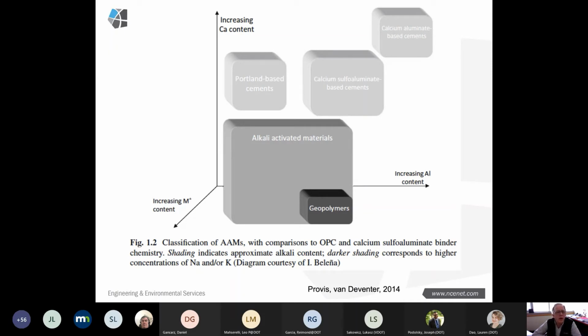And as you see, if you move up on the z-axis, go up along the screen, you see increasing calcium content. And generally speaking, as the calcium content in your cement increases, you're going to see it be more of a hydraulic cement. And then as you start moving out along the basal plane here, M plus is indicating sodium and potassium, or alkali minerals, and then moving along the other axis, increasing aluminum content. And so if you move out away from the origin, if you move towards more aluminum, you can get what is actually a geopolymer, which is a specific type of reaction that occurs. As you have less aluminum, but limit the calcium and increase the alkali, you're going to get alkali activated materials.